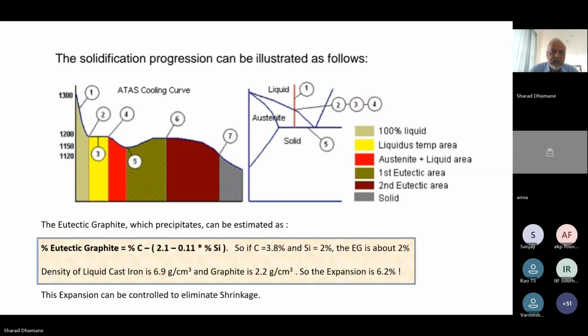graphite will come out. So here there is a formula. This formula gives eutectic graphite as a function of the percentage of carbon, and the percentage of silicon is also involved. This is a simple formula. If you want to add the effect of manganese and other elements, it will change slightly, not much. So more accurately, almost confidently, you can use this formula to understand the amount of eutectic graphite which is expected to come out during solidification. Just an example: if your carbon is 3.8% and your silicon is 2%, then your eutectic graphite is about 2%. So just imagine 2% of graphite is going to come out during solidification.